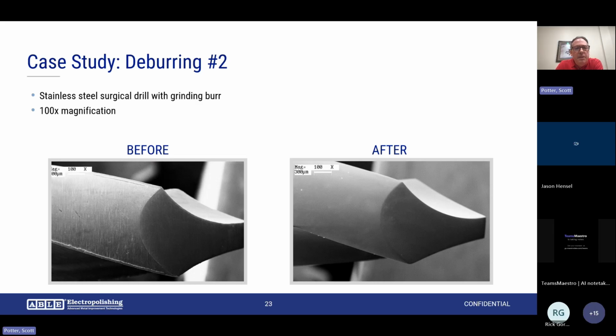Here's a stainless surgical drill with a grinding burr. You can see that lateral burr there. This is at 100 magnification. You can see how the electropolishing cleaned up those edges. One of the questions people have is how much radius you get on an edge, and typically the radius that we achieve is twice that of the stock removal. So if we're taking 5/10,000ths off a thickness or diameter, you're going to get about a thousandth radius. It's a rule of thumb. It's a slight break, enough to take that burr off and put a slight radius on there.